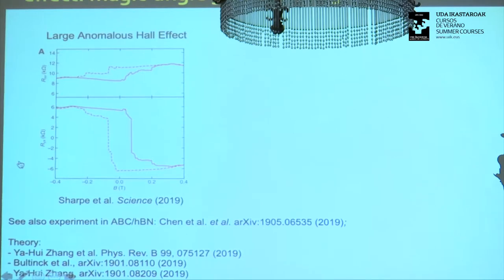Now, it's a little bit tricky because if you just take regular graphene, one layer, and put it on hexagonal boron nitride and align it, you open a gap, but you make a trivial insulator. But twisted bilayer graphene has special characteristics. The Dirac cones in twisted bilayer graphene are such that when you gap them, you go into a topological insulator, not a trivial insulator. This has to do with the details, and you can ask Mike Zaletel or Andrei Bernevig for more information, but it has to do with the phases in the Dirac cones, the two sets of Dirac cones that you get when you align this. They happen to be different from what you have in monolayer graphene for the two valleys. So this was a very interesting development. It just got published in Science a few weeks ago.